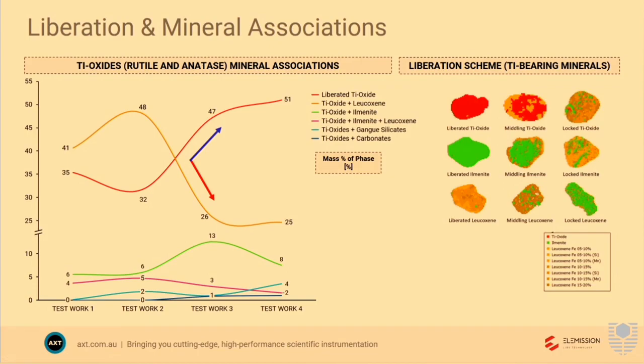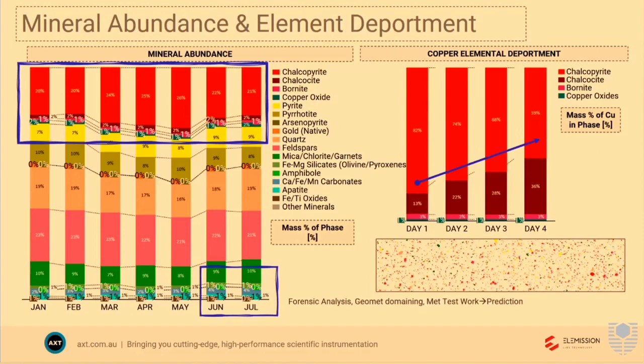So you've got XRD that gives you bulk mineralogy, gives you the crystallinity. It's a very fast method of analysis. These samples here require setting in resin, or if they're a large enough mineral sample, you don't need to set it in resin, but it's got to be a certain size. You polish it, carbon coat it, and put it in the scanning electron microscope instrument. But you get quantitative mineralogy, mineral chemistry, mineral associations, and texture. So depending on what you want. The software is designed for the process metallurgist.